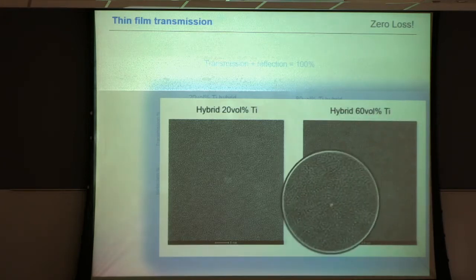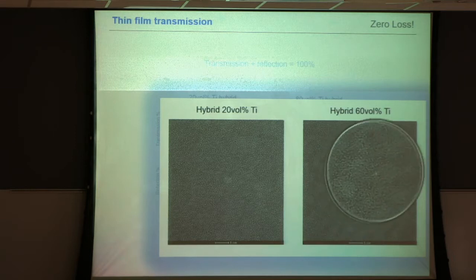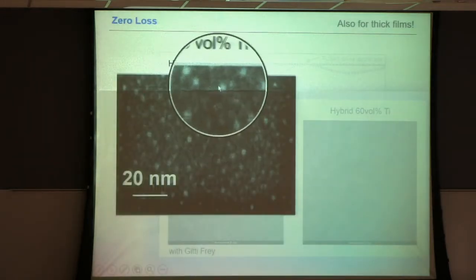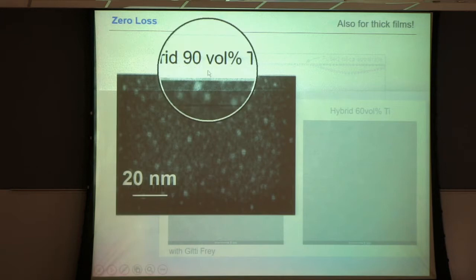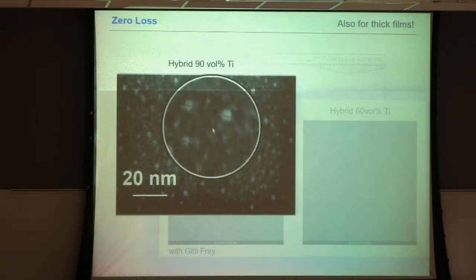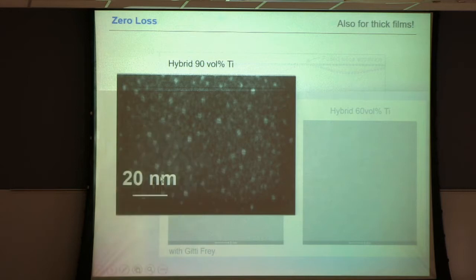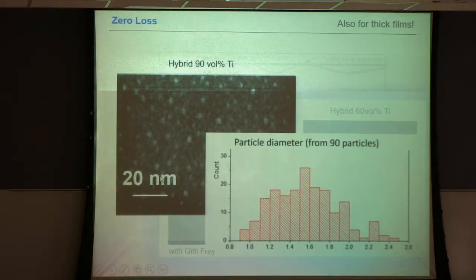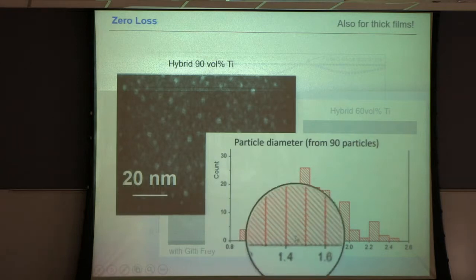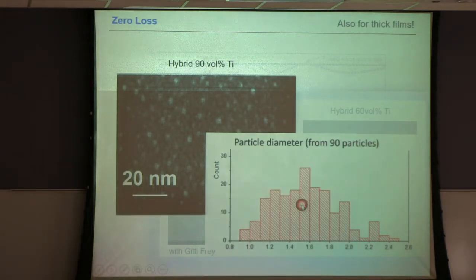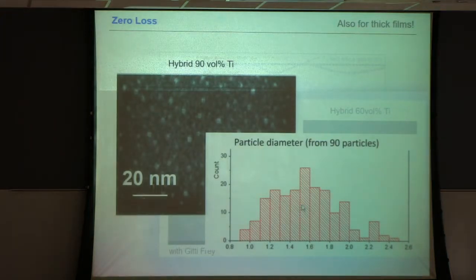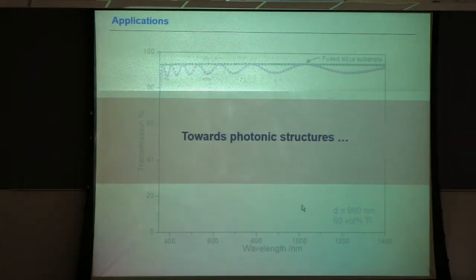Anything amorphous that you would stick into the TEM would look like that. Here, maybe you start to see some brighter areas, but it could just be also the picture. Only when we go to the very, very high content material, 90 volume %, do you really see particles occurring. But look here at the scale bar, 20 nanometers. So the particles at the very high content material are still around 1.5 nanometers. So these will not affect optical properties down to very low wavelengths. That explains the high transparency of the material.